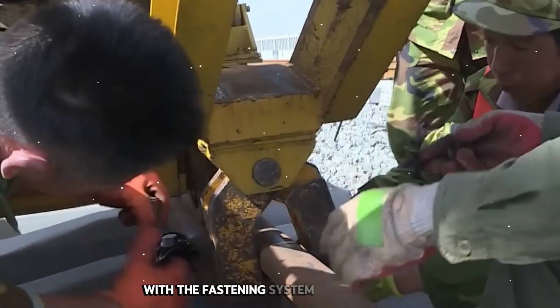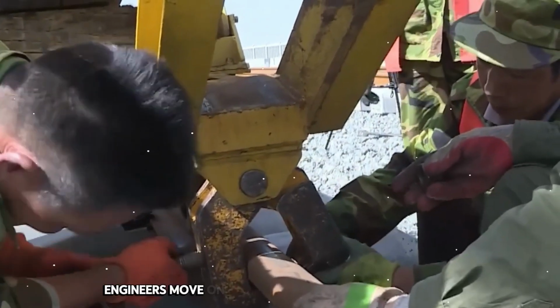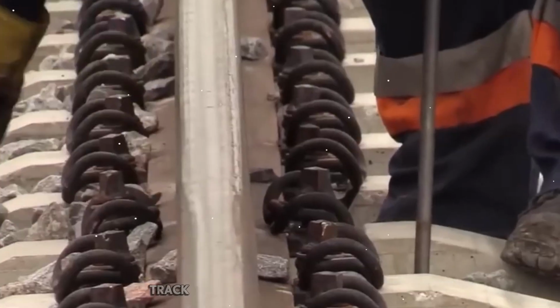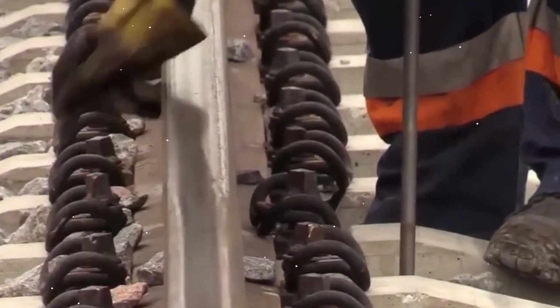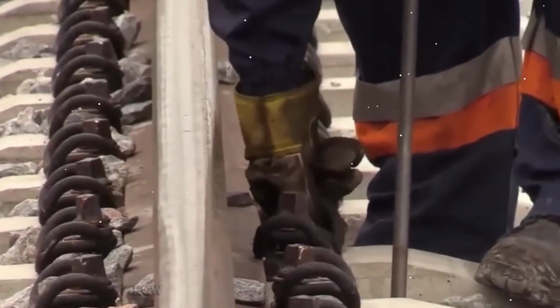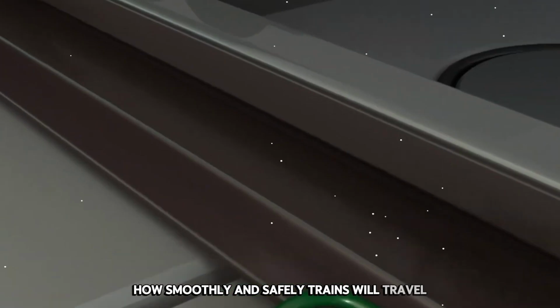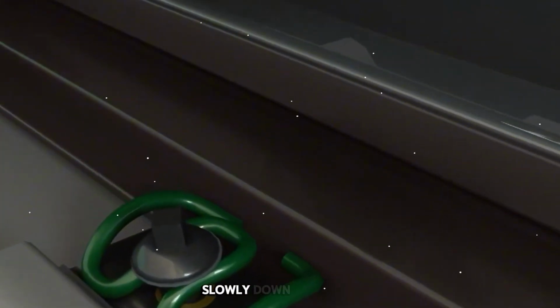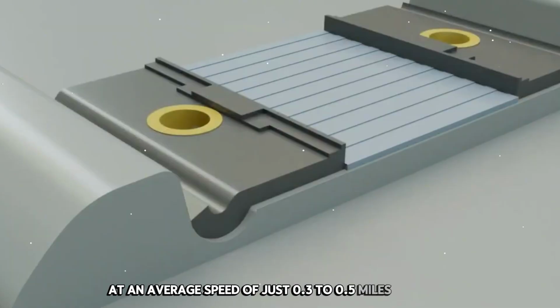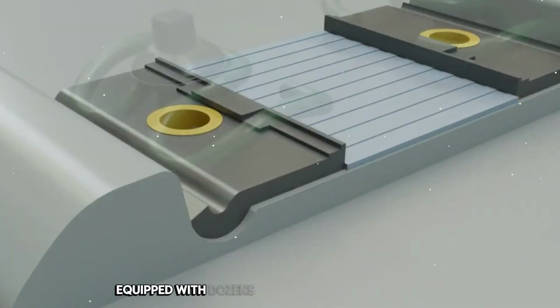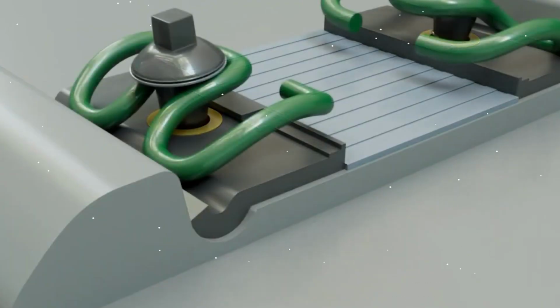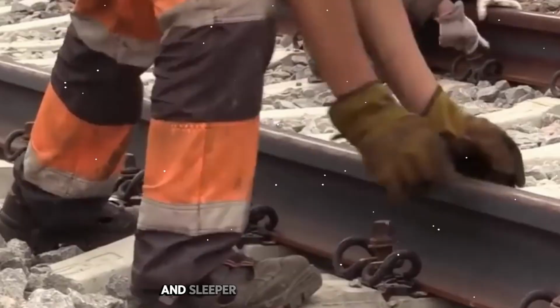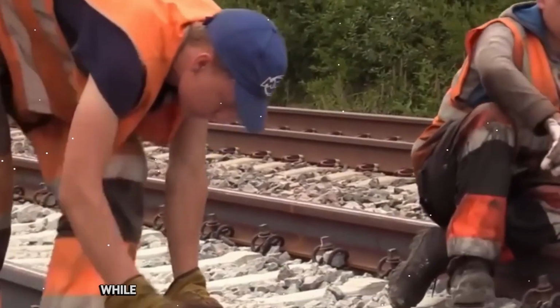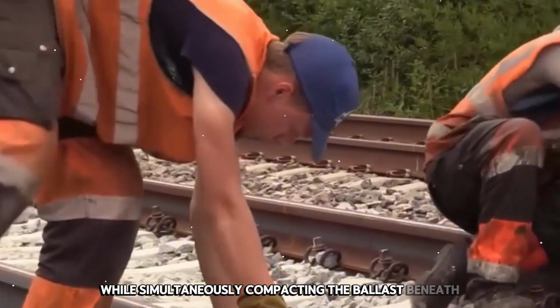With the fastening system fully installed, engineers move on to one of the most critical stages: track alignment and ballast tamping. This precision process determines how smoothly and safely trains will travel along the rails. A specialized tamping machine advances slowly down the track at an average speed of just 0.3 to 0.5 miles per hour. Equipped with dozens of hydraulic vibrating tines, the machine lifts the entire rail and sleeper assembly by 1 to 2 inches while simultaneously compacting the ballast beneath.